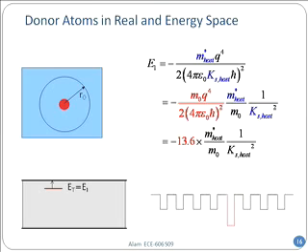And therefore, when you look at the level where this atom sits, it's a bound level, so it's a little bit lower, about, let's say, 13 millielectron volts. It's very close. What is the band gap? Band gap is about an eV. And that electron sits about 13 millielectron volts from the band. That's how this electron is so easy to detach. Had it been pure hydrogen, you would need 13 electron volts to make the electron go. Here, 13 millielectron volts, and at room temperature, kT is 25 millielectron volts, right? So even at room temperature, most of them will escape from the bound level, you see.